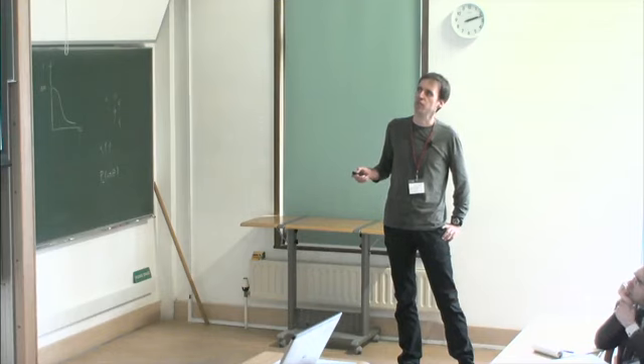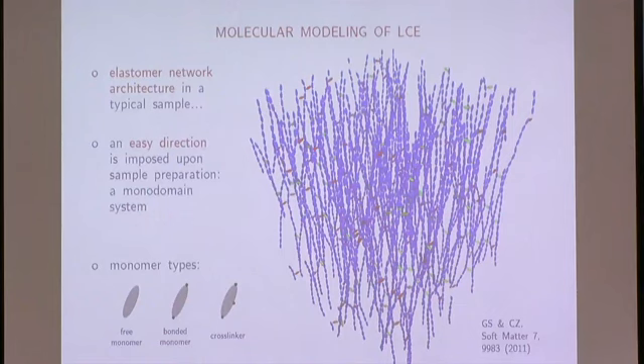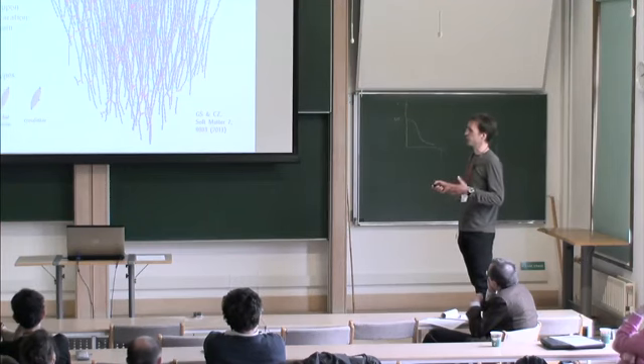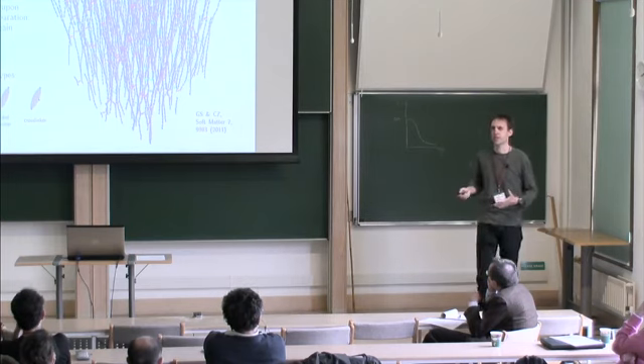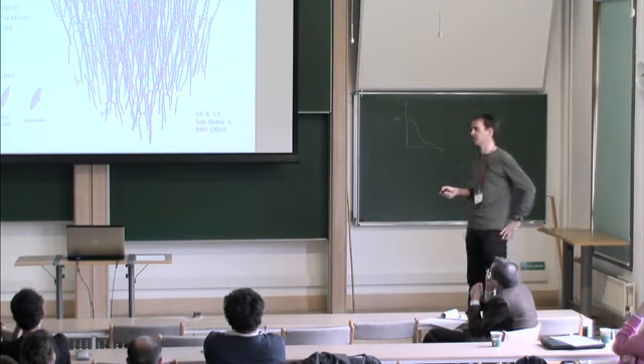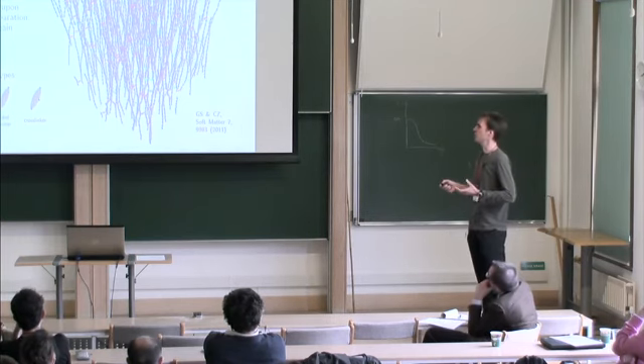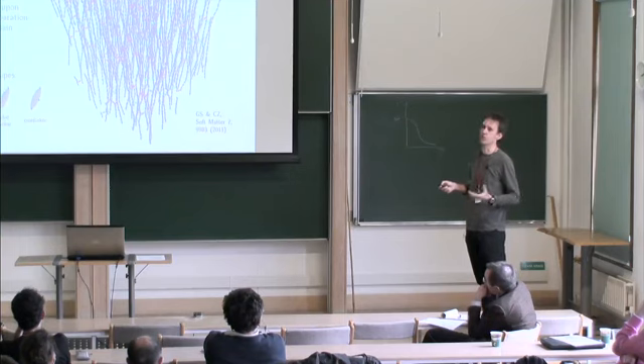Of course, they have to be cross-linked, so they are cross-linked with this red and green, let's say, monomer, with these red and green ellipsoids that you can see here. And in this way, as you can see, mostly blue color is prevailing. So what's obvious is that in this way, we have imprinted an easy direction along the z-axis, and this is somehow our substitute for following the two-stage cross-linking procedure.